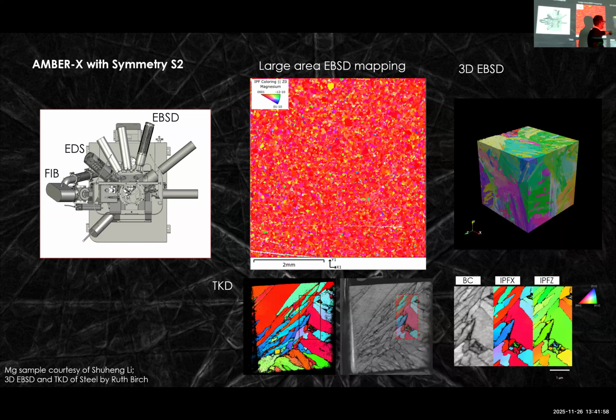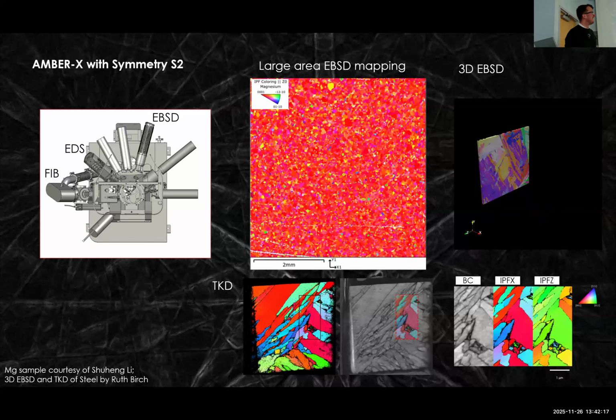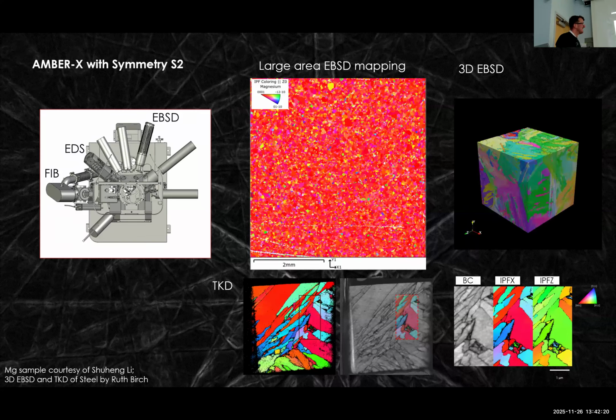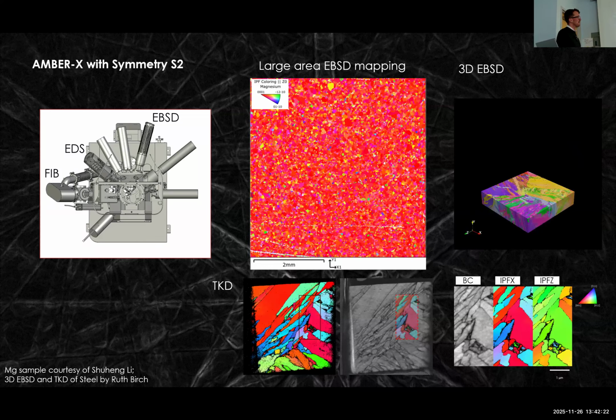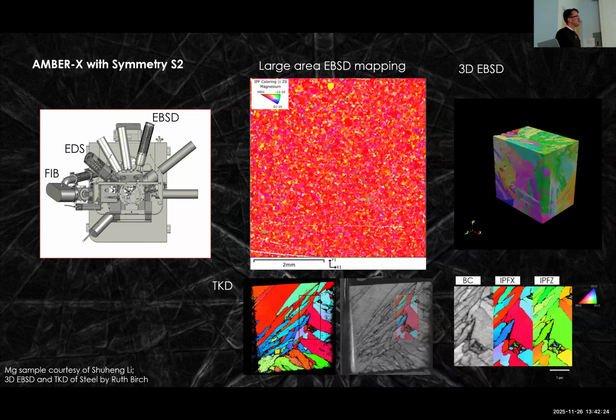This is the 3D data set that I've just shown you. And then this is a TKD data set, and the scale bar there is 1 micron. There's that little field, and the whole area was mapped in that foil. This is a TEM lift-out that was done on the PFIB on steel, I think, in this case, for that example. Oh, there's the slice and wipe. Apparently it does appear. So that's the 3D slice and wipe. Kind of nice.